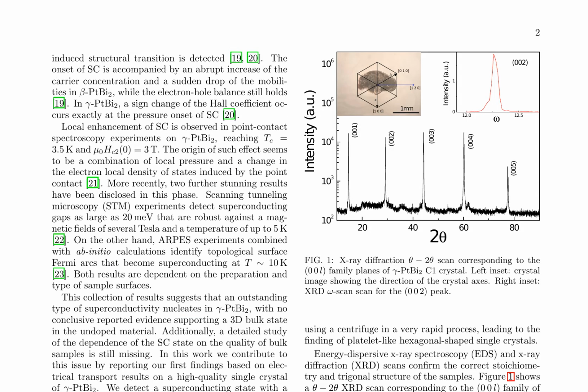The onset of superconductivity in beta PtBi2 and gamma PtBi2 is characterized by an abrupt increase in carrier concentration and a sudden drop in mobilities. In gamma PtBi2, a sign change in the Hall coefficient occurs exactly at the pressure onset of superconductivity. Local enhancement of superconductivity is observed in point contact spectroscopy experiments, with a critical temperature of 3.5 K and an upper critical field of 3 T.